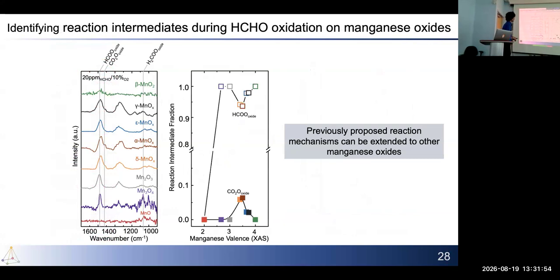We tracked the relative intensities of the two main intermediates: the carbonate intermediate shown at the bottom, and the formate intermediate at the top. Interestingly, we see that both of them have opposite trends, and they peak at around 3.8 manganese valence in opposite ways. So the bottom of this is sort of the top of this. This is a really interesting trend.